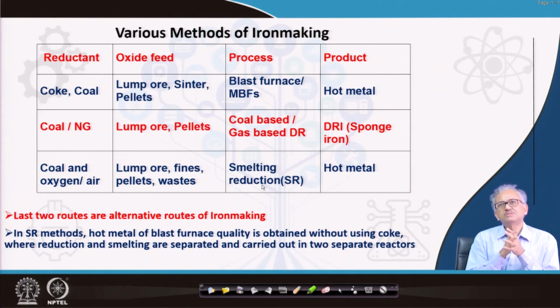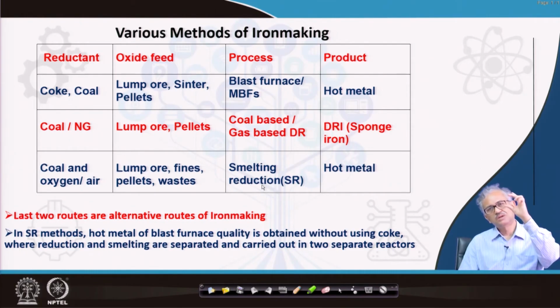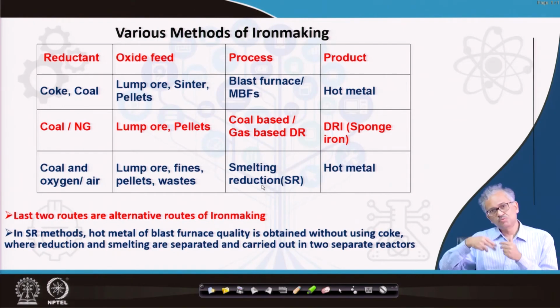Why? Because the blast furnace is a complicated reactor. As I said, you have a dry zone, then a cohesive zone, and then the liquid zone. You have to maintain this. You have to correlate these three zones so nicely that the whole reactor operates very smoothly. Otherwise, a lot of irregularities like channeling and flooding take place in the blast furnace if you are not cautious about the operating parameters and the burden material. So these factors make the blast furnace very vulnerable.